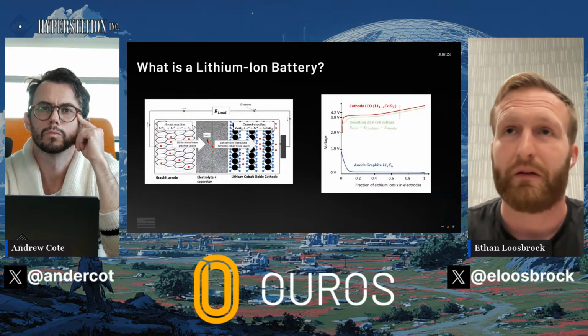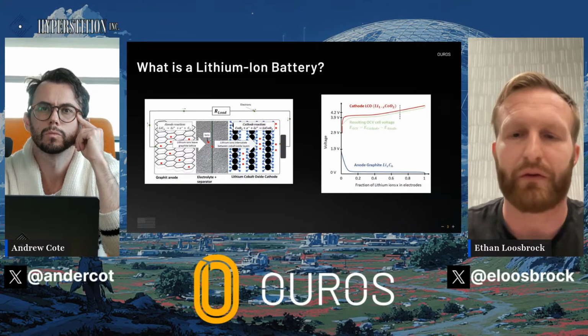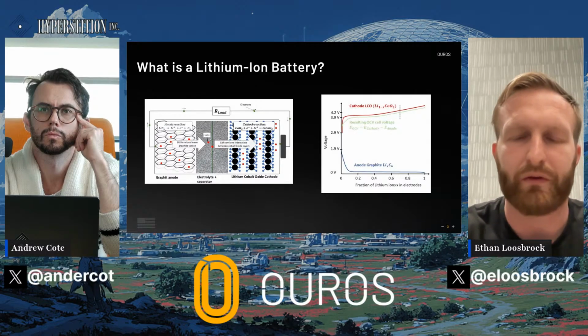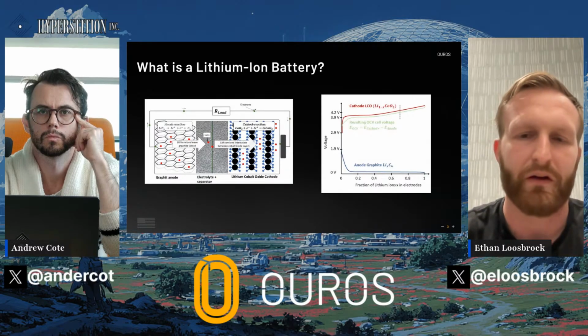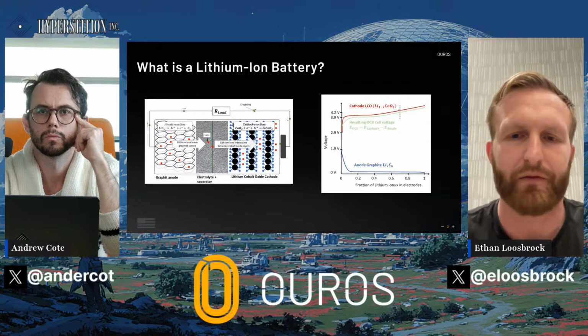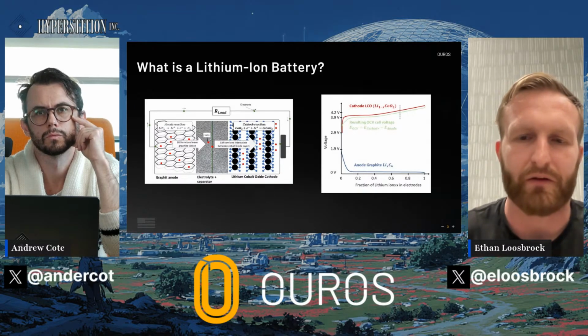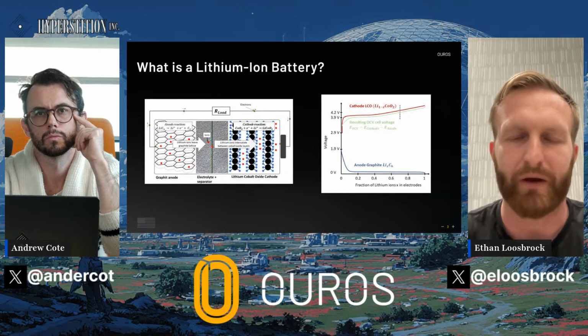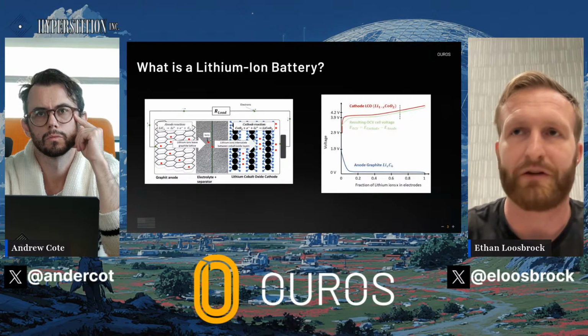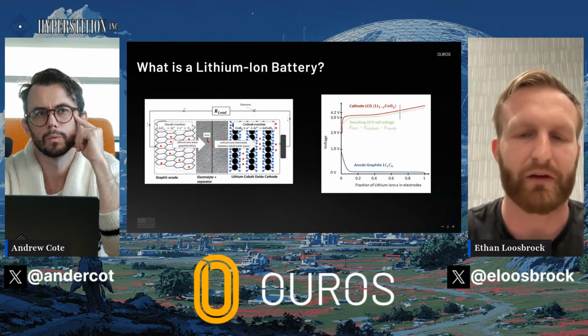Typically the best batteries out there, like an NMC graphite cell, will lose a full 10% of their energy that first cycle, and it's irreversible because you're consuming some of the lithium to make this layer. And then after that first cycle, or maybe you do a few formation cycles, your coulombic efficiency will be at least 3 nines, 99.9, and for the best cells, you're looking at 5 or 6 nines.